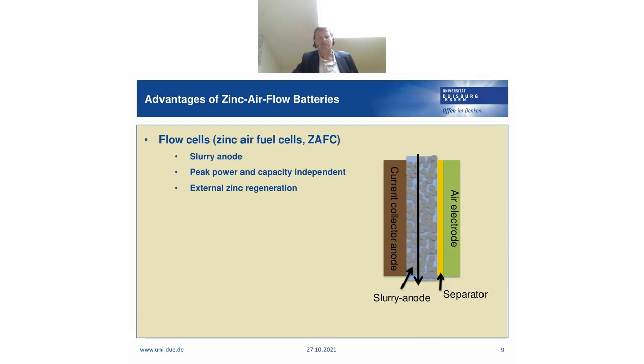Flow cells, as I've just introduced to you, have this setup as depicted here. We have a current collector on the anode. Very often we use a copper current collector. Then we have the slurry anode, which is pumped through the cell, and you see all these 50 or 70 micrometer zinc particles. They are interconnected. They form a percolation network. And then we have here in yellow the separator, and in green the air electrode.